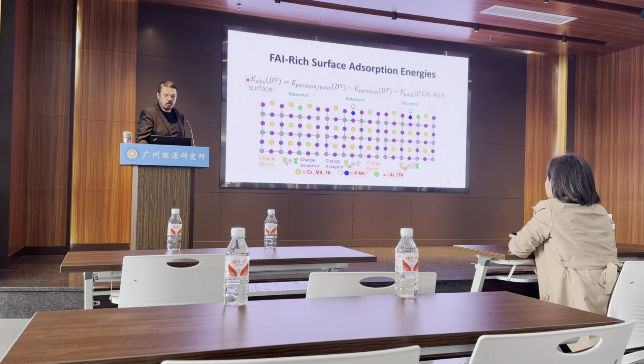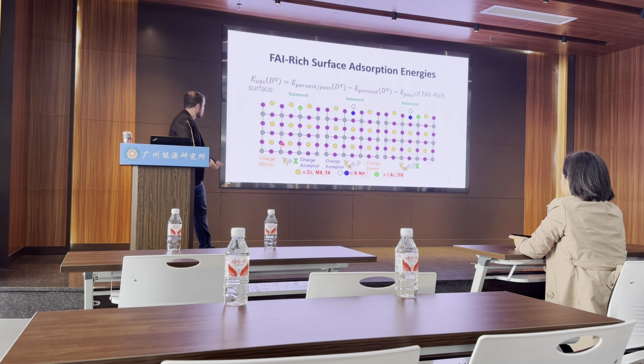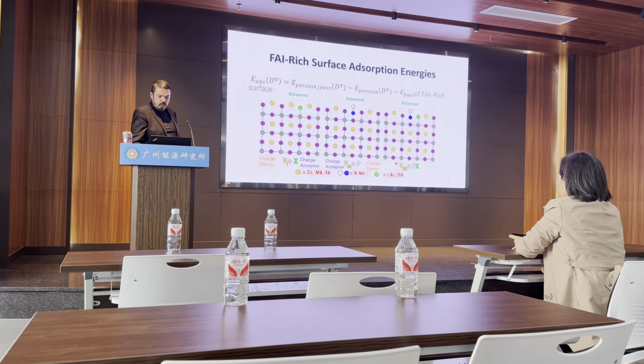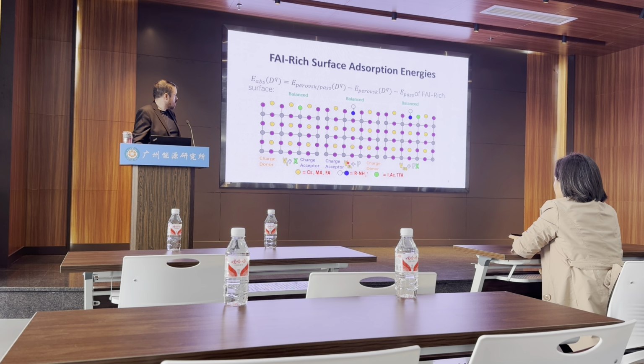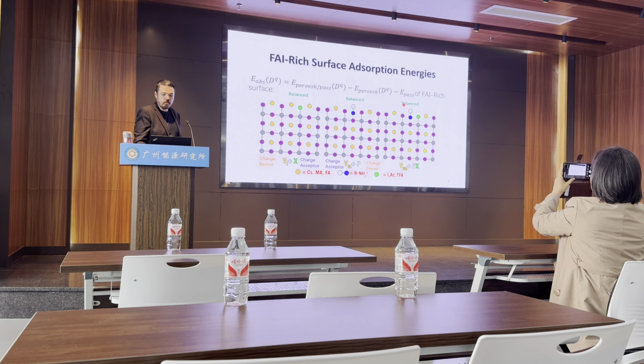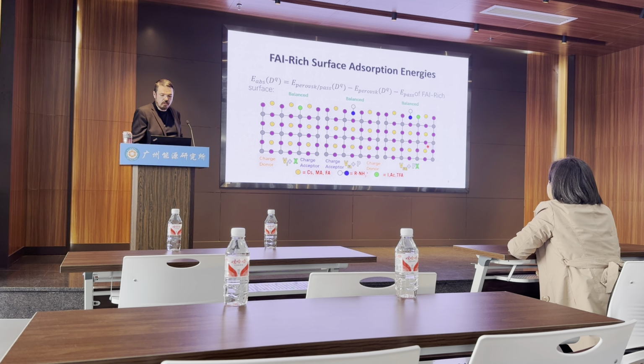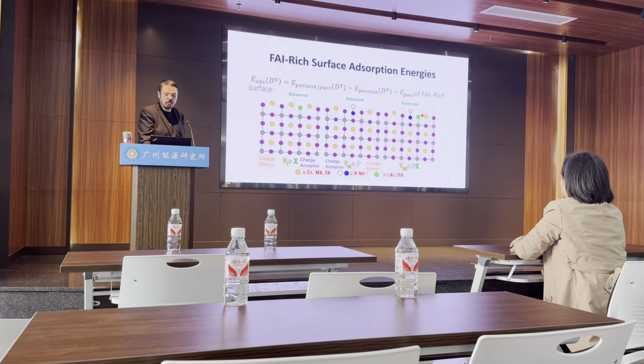So the formamidinium iodide-rich surface, you can see that, for example, we can take our anion and replace the surface-based iodine with it. So basically, we're filling an iodine vacancy here. Iodine vacancy. In the central one, we can do a formamidinium vacancy. So here we put a charged donor in there, so the amine. And finally, we can fill a Schottky defect. So this is when we put the whole salt into the vacancy. And these are actually common. I'll explain later. So this is actually a very good model for the real world device.